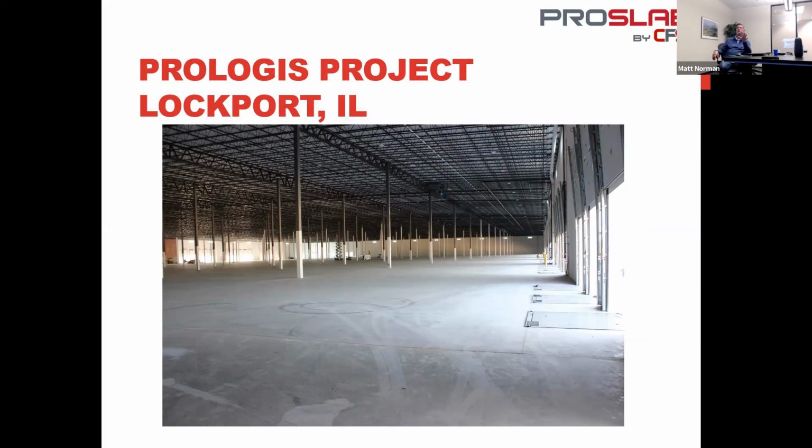Now, the key to producing this type of floor is that you want your panels to be able to move freely. So you're going to put a slip sheet on the subgrade. It's not a vapor barrier, it's a slip sheet. That's what we name it. It's anywhere from 4 to 6 mil thick polyethylene sheeting, and it's simply there to reduce the coefficient of friction between the subgrade and the slab.